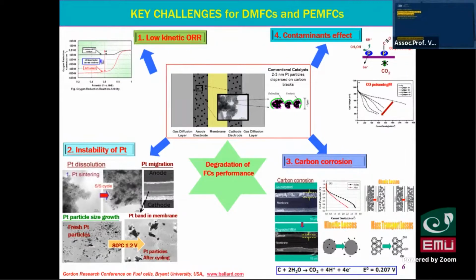So this affects the efficiency of the fuel cell - this is the second problem. And the third problem is carbon corrosion. During fuel cell startup, stop, and shutdown, with different potentials, carbon can oxidize and become CO2. This reaction happens at a potential of 0.2 to 0.74 volts. If carbon corrodes, we lose the platinum catalyst.